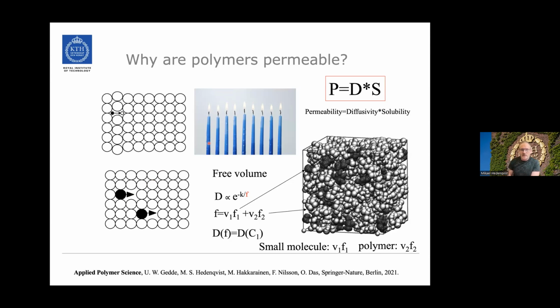So that is a very tight material. And one can consider it as a low molecular weight polyethylene. But as we go into larger molecules to polymers, they are not able to arrange in 100% crystalline fashion. So there will be amorphous regions, and there you have free volume.